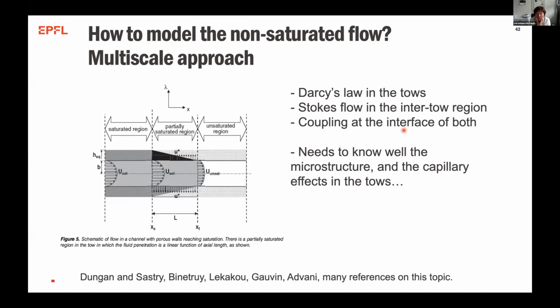So we can use a multi-scale approach, which is normally what people have done, and there are, again, many references on this topic, is to say, well, I have fibers here, I have a gap here, and I can model the flow. In this case, for example, the flow is going faster in the gap and slower in the tows. And I have some transverse flow that's going here. And I do a coupling at the interface between the Darcy's law in the tow and the Stokes flow in the region in between the tows.